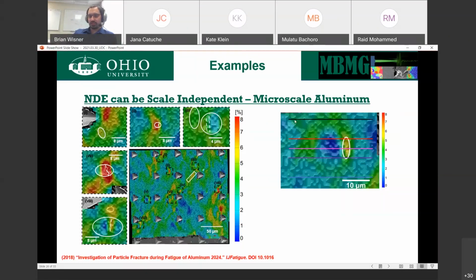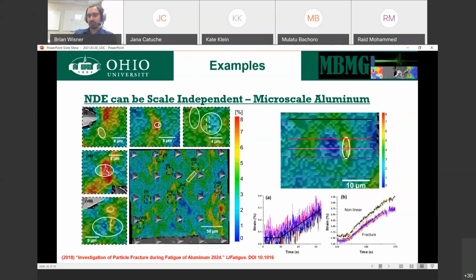These lines that you see here, just to illustrate the power of DIC, each one of these lines represents a location where a virtual extensometer was placed. And what we see is when we initially load, the whole area behaves the same. So in the elastic regime, our thought process that the material is behaving isotropically is fairly accurate. But as we continue to load and we start to get into plasticity in some regions, we start to notice that there's a difference in behavior at different locations of this material. Not only that, but in some cases, we start to get nonlinearity. So we know there is an effect. There's an effect of this particle on the way the strain is evolving.